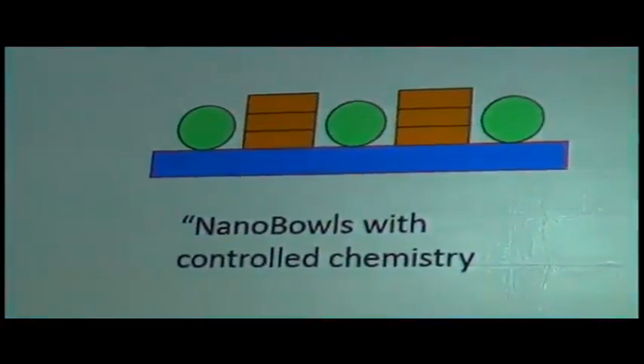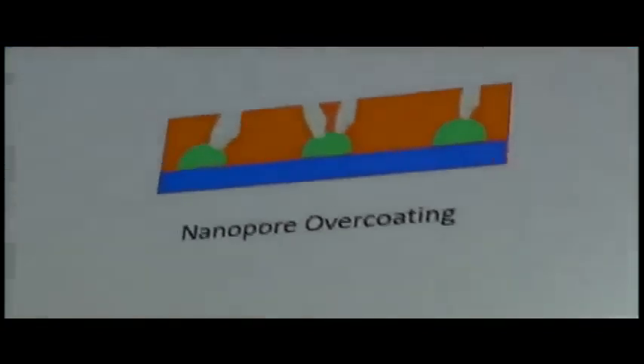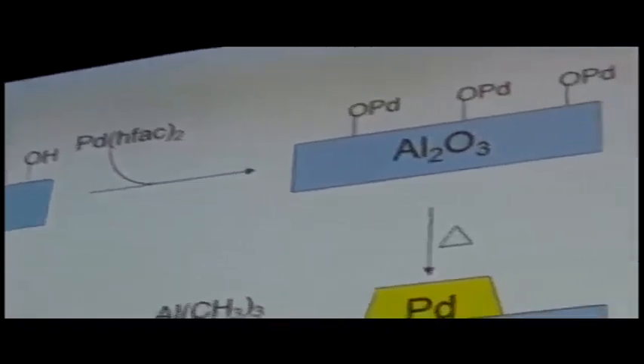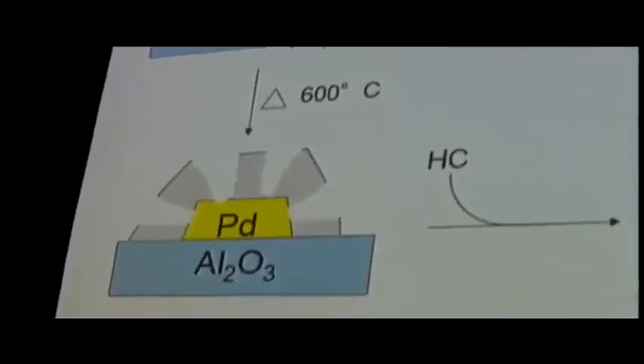What I'm going to talk about this morning in the talk is what we call overcoating of these materials, in which we've actually put various components such as aluminum oxide over the top of the metals, okay, to form new pores on there and control the interaction with the surface of the catalyst. The overcoating is basically the next step beyond what I just talked about. You can see in the first portion there, we can make palladium particles, for example, on the surface of aluminum oxide, overcoat those with aluminum oxide, but when we then calcine those materials, we actually form new pores into the catalyst.